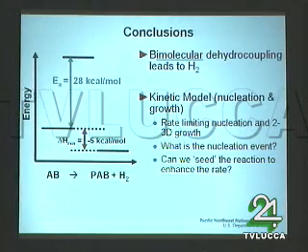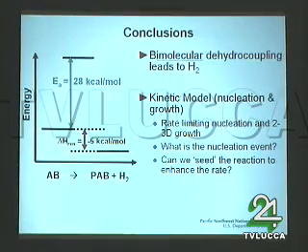So the conclusion, I think I summarize it best with an energy level diagram here. We've got an activation barrier of 28 kcals for the rate limiting step, starting with pristine material. And the heat of reaction is 5 kcals per mole exothermic. So that's the other interesting thing about this compared with carbon systems, which are endothermic for release of hydrogen. This thing is exothermic with release of hydrogen.